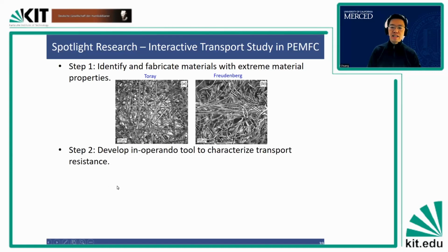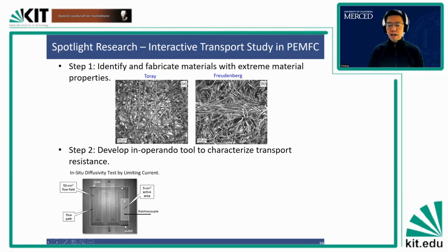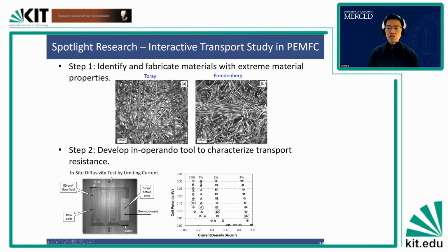The second step is that we develop in situ or in operando tools to characterize transport resistance. This is referred to as the limiting current process. It was first developed by General Motors. As you can see here, we change the concentration of oxygen. We can also change the concentration of hydrogen and identify the transport resistance of this gas diffusion layer, which refers to this R, resistance. In this case, it is oxygen, but of course we can also study hydrogen. We measure this limiting current, which is the dot in the center, and we control the concentration.